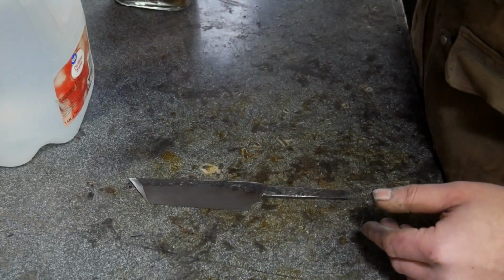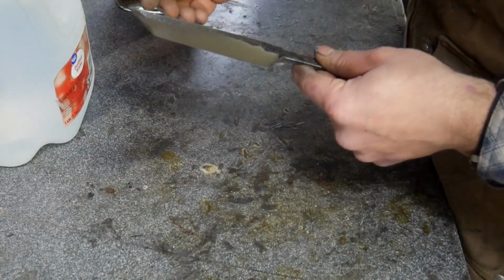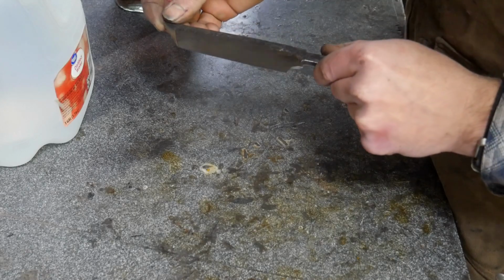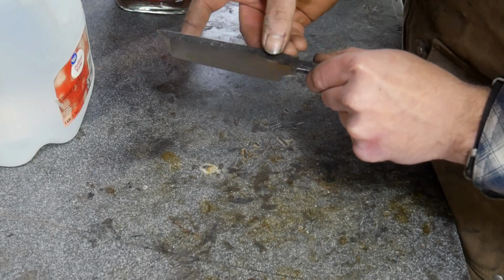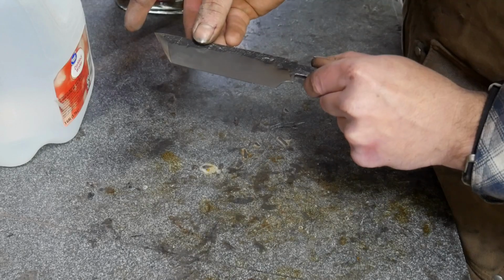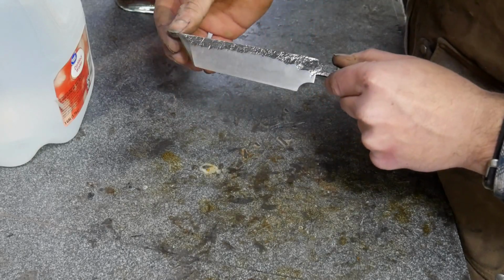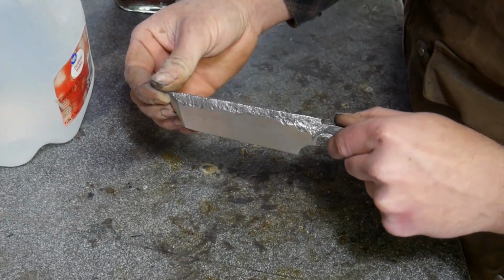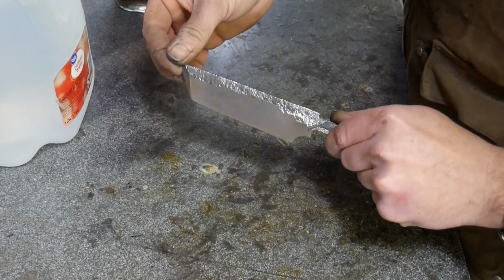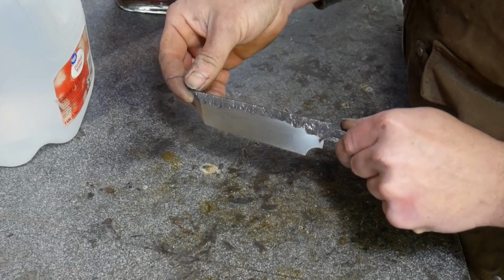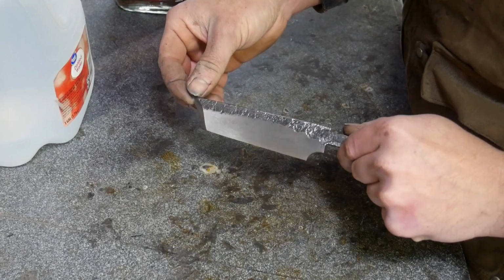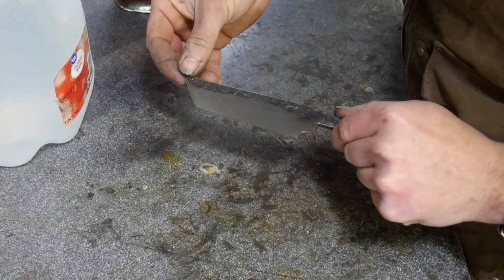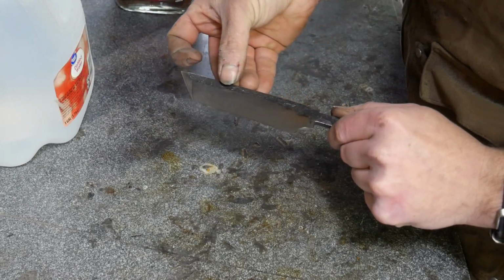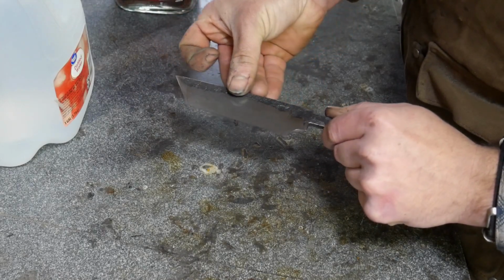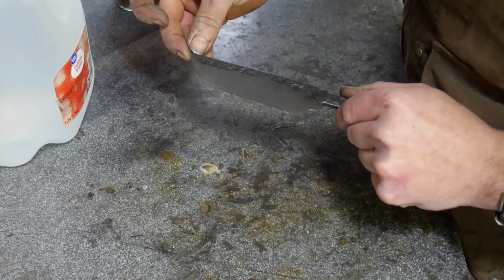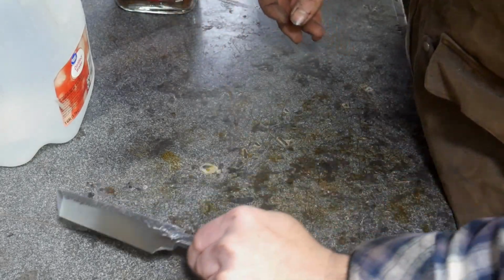Over time, it will tend to get darker, and that is because in the forge welding process, enough of the carbon in the 15N20 and in the 1095 kind of get pulled into each other that you will start to get a little bit of dark on your 15N20 if you're not careful. So that's why when we put it in our solution here, you want to make sure you check it every hour or so and make sure that only your Damascus where you want it is getting black. And as soon as that 15N20 starts to darken, or as soon as you have a really good coating on your 1095 or 1084, you pull the knife and clean it off.